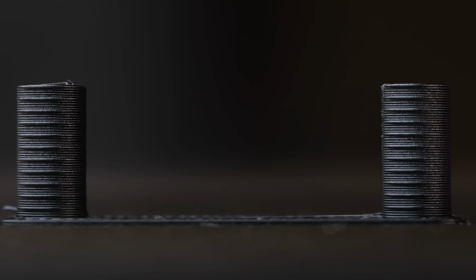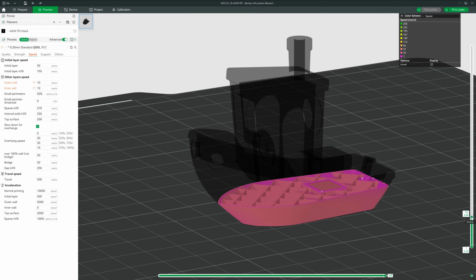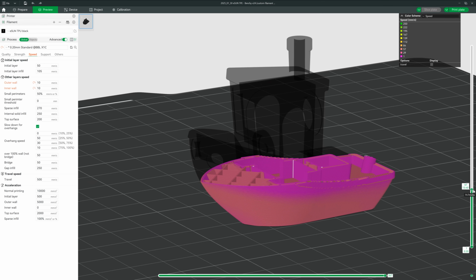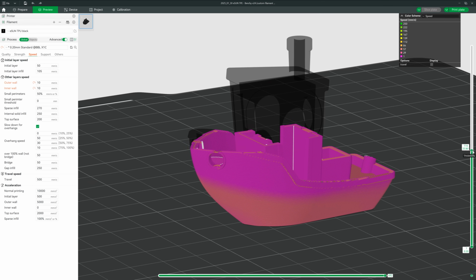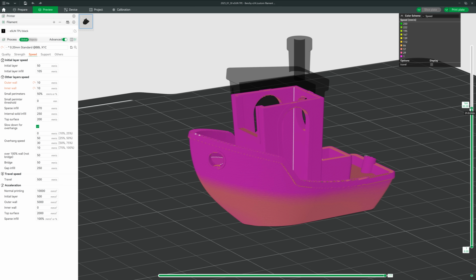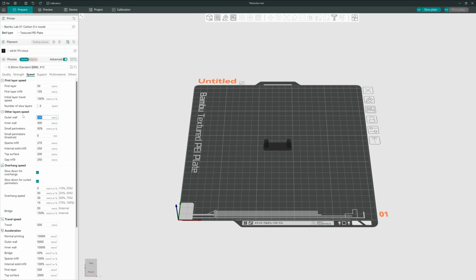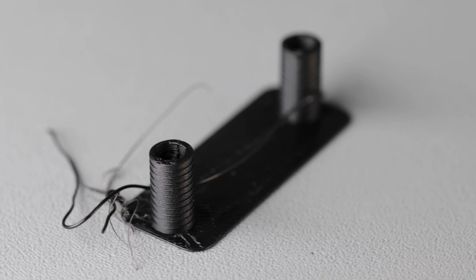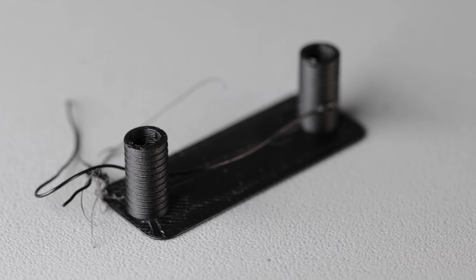In the retraction test we had 0 stringing. Well, print speed affects stringing too. When printing slowly, the filament spends more time in the nozzle and gets hotter. And the hotter the filament, the higher the risk of stringing. To prove this theory, let's rerun the retraction tower test, but this time we will slow down the print speed to 10 mm per second. And guess what? Now we see tons of stringing.